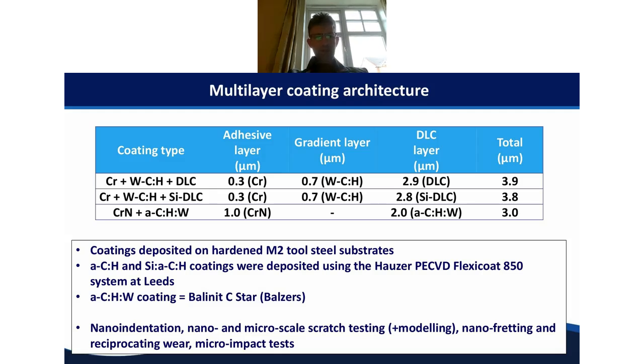So we're going to be looking at 3 different coating systems. One has an undoped DLC top layer, another a silicon doped DLC top layer, and another a tungsten doped DLC top layer. These have all been deposited on hardened M2 tool steel substrates, a couple of them with the Hauzer system at Leeds, and one was a commercial system.